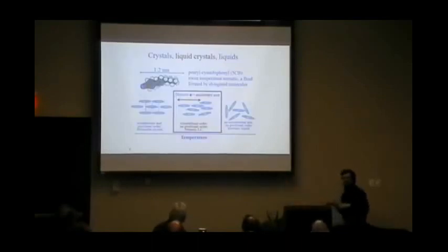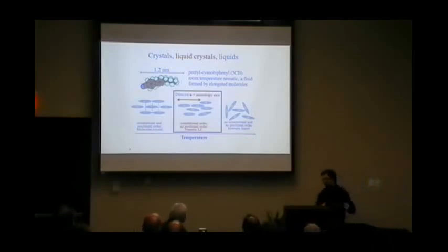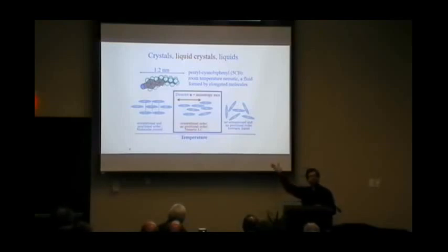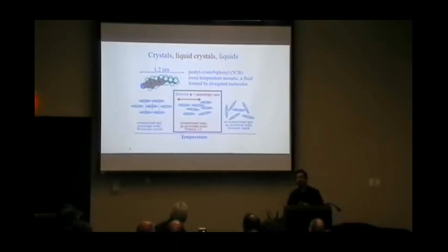So this is the basic thing number one about liquid crystals. You might have an organic crystal that has long-range positional order and long-range orientational order. And then if you heat it, many of those organic crystals would show two-stage melting. First, they would lose the positional ordering of the centers of mass of the molecules, and they will form, in many cases, the simplest type of liquid crystal, the so-called nematic liquid crystal shown here. The only type of ordering here is long-range orientational alignment of the long axis of the molecules. And then if you increase the temperature further, you would get the second melting, and your material will be simply an isotropic fluid in which the molecules are free to rotate and not just to move around.